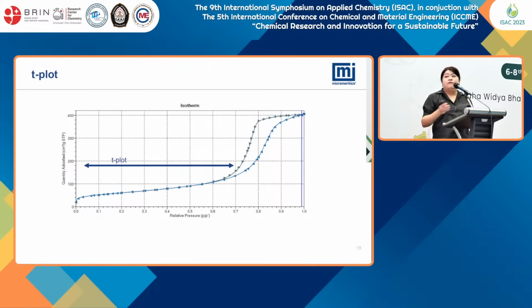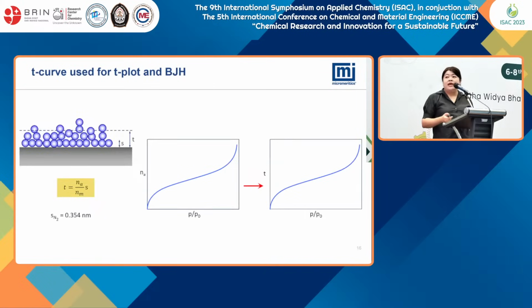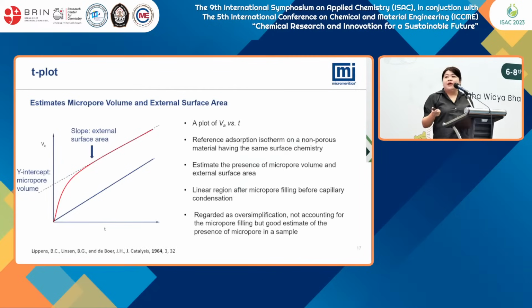Okay, so moving forward, if you were to continue the pressure to a higher pressure, you'll be able to analyze T-plot. In T-plot model, you are using the T curve for the T-plot and the BJH, where you are looking at multi-layers starting to fill. From there, you are able to estimate the micropore volume and the external surface area of the sample. The linear region after the micropore filling, or before the capillary condensation, is what's analyzed using T-plot.